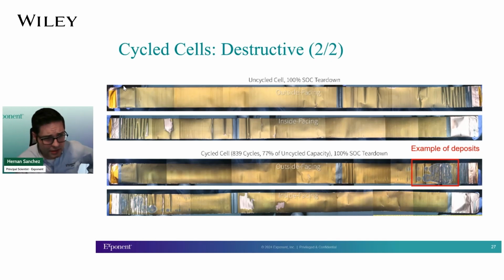Another aspect, and it was nice to see in the previous talk, this whole discussion about understanding in air-free conditions, is just doing cell teardowns of cycled and uncycled cells. Because that's where, once again, guided by the CT scanning, you can then see if this is a cell that's worth doing a teardown at 100% state of charge, because that's where you will have your potentially worst case scenarios, when you are fully charged, as opposed to if you discharge the cell before unrolling it, where sometimes you might lose some information.